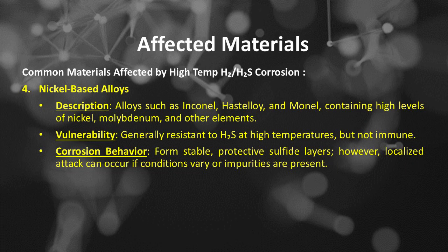The affected materials, number 4, is nickel-based alloys. Alloys such as Inconel, Hastelloy, and Monel, containing high levels of nickel, molybdenum, and other elements. The vulnerability of the nickel-based alloys: generally resistant to H₂S at high temperatures, but not immune. The corrosion behavior of high-temperature hydrogen (H2) and hydrogen sulfide (H₂S) corrosion on these nickel-based alloys is they form stable, protective sulfide layers. However, localized attack can occur if conditions vary or impurities are present.